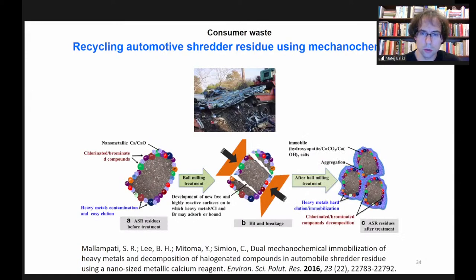One more slide from the consumer waste. Automotive shredder residue is quite a big environmental problem because it contains chlorinated and brominated organic compounds and also heavy metals. And if it is just stored like this on the picture, they can easily, of course, pollute the environment. So the authors of the work I am referencing introduced nanoscale calcium oxide into the mill together with the residues of this automotive shredder. And what happened was that this calcium oxide encapsulated the automotive shredder residue particles. As the result, heavy metals were not leached out anymore, and the chlorinated and brominated compounds decomposed.